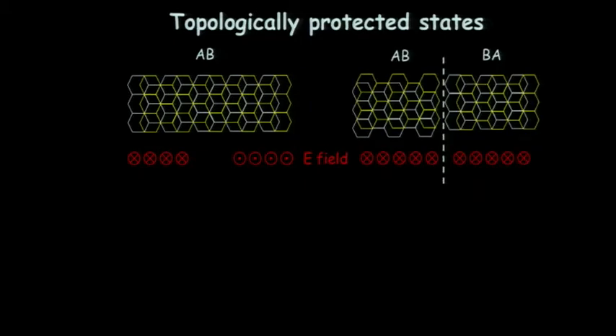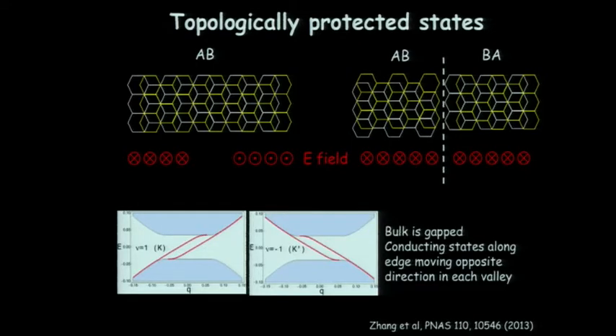That's equivalent to applying a uniform electric field by going from AB region to a BA region. If you just change the stacking configuration but leave the field profile the same, the same effect will happen. You'll have a gapped region here, a gapped region here, and a conducting region on the inside. And so there have been calculations, I guess, 5 years ago on these systems. In the bulk, we have this gap state, and there should be 2 conducting channels moving along the boundary here, and they are moving in opposite directions in the K and the K prime valley. So these are topologically protected states at this interface between these stacking configurations or along the 0 line of the electric field if you had uniform stacked graphene.